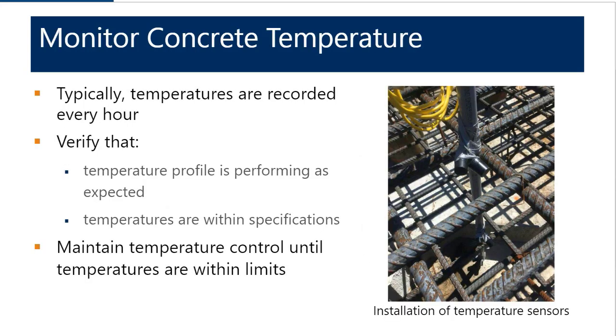So after the concrete is placed, you want to monitor the internal temperatures of the concrete element. And so typically the temperatures are recorded every hour. And the purpose of this exercise is to verify that the temperature profile is performing as expected, meaning that the in-place temperature measurements are aligned with the theoretical temperature profile that was calculated during the analysis that was part of the thermal control plan. And ultimately, these temperature measurements will typically be submitted to the design team to confirm that they were within the project specifications.